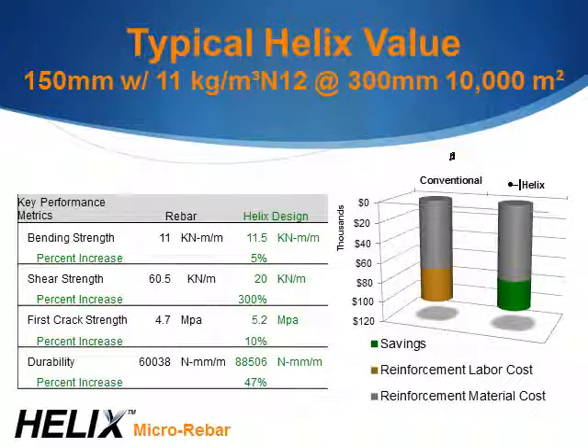So this is just an example. Typically, bending strength governs, but anytime you put Helix into a concrete mix, it actually increases the amount of shear resistance in the concrete without even adding any additional Helix, because it's providing reinforcement in all directions, and shear is just tension at an angle. It also increases the first crack strength of the concrete. It makes it a little bit harder for it to crack, and it increases the durability, which is the area under that curve we were talking about before. So it saves money, and it gives really a better, more durable piece of concrete, as well as all the peace of mind of having a fully peer-reviewed design method that we stand behind to base your analysis and alternative calculations on.